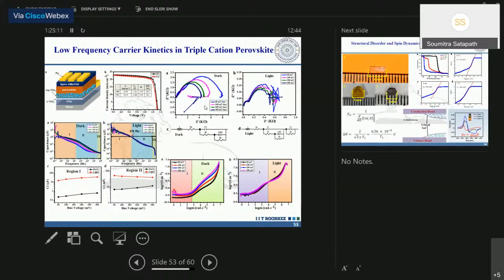And what we found out is that even for this high efficiency cell, a negative capacitance exists. It's a very, very interesting thing. Negative capacitance is nothing but an inductive element in your LCR circuit. If you draw an equivalent circuit, a negative capacitance corresponds to an inductive element. It has been reported that in perovskite solar cells, negative capacitance originates at low frequency only. But what we have observed is that it is also observed in the high efficiency device. That means frequency and stability do not matter, but the negative capacitance is an inherent property of this material.